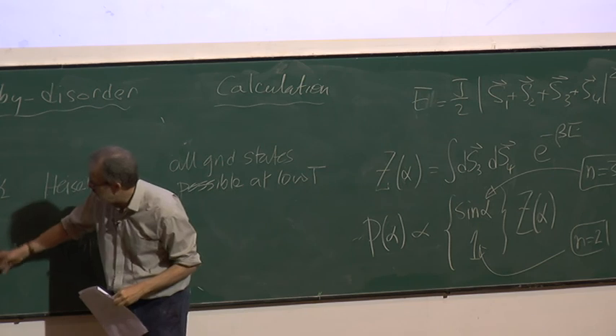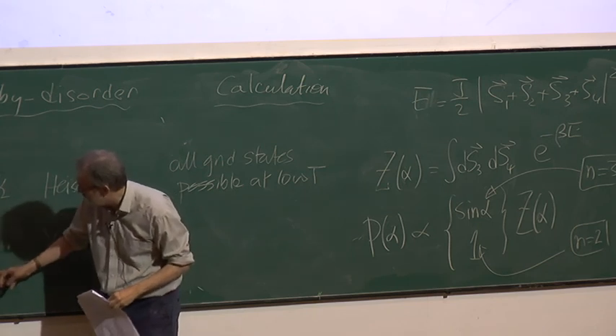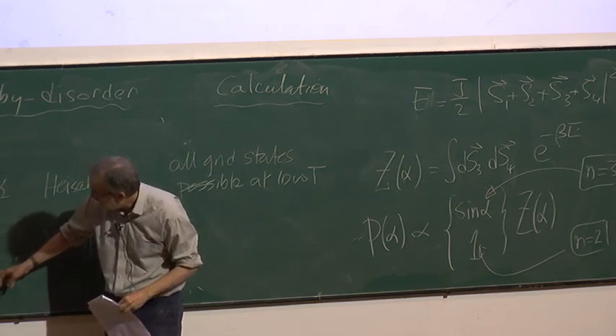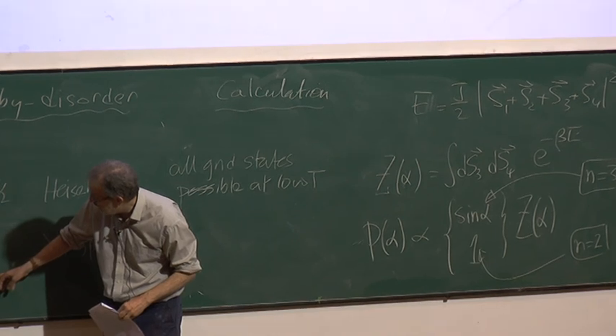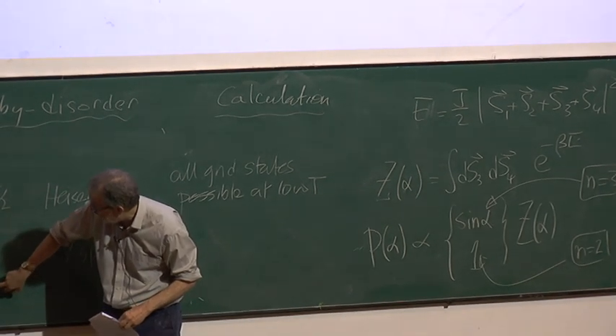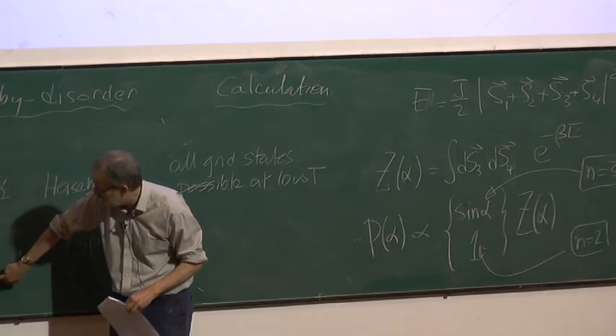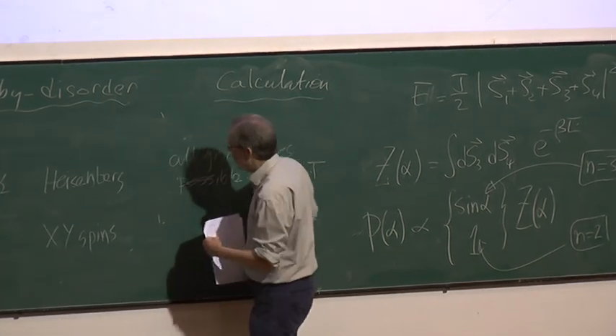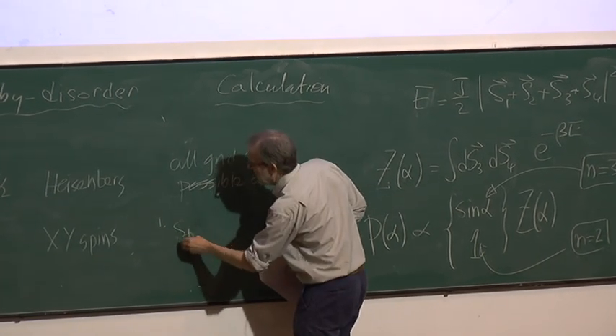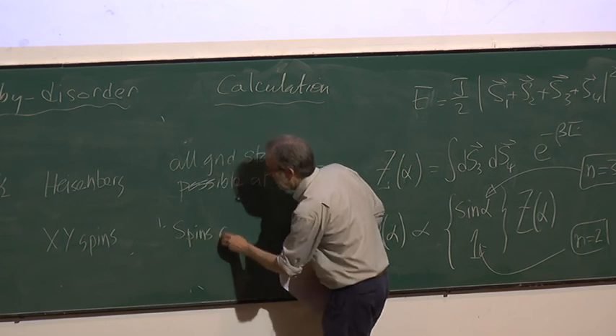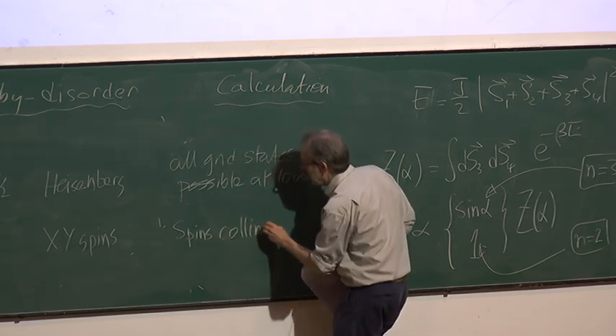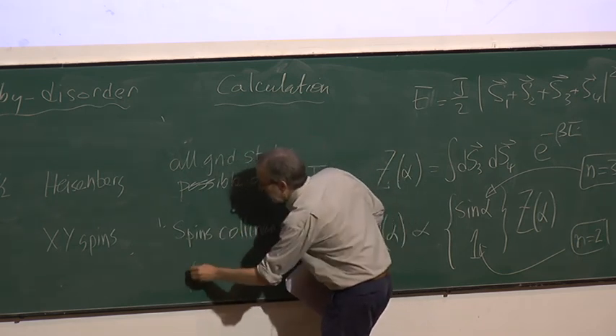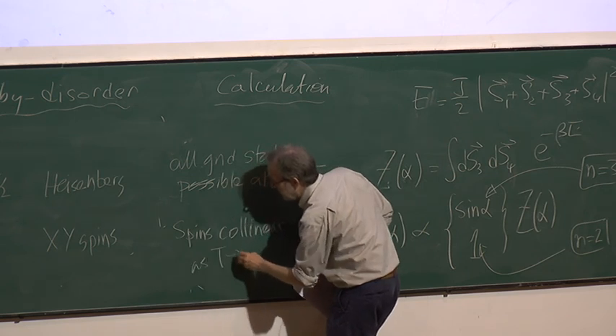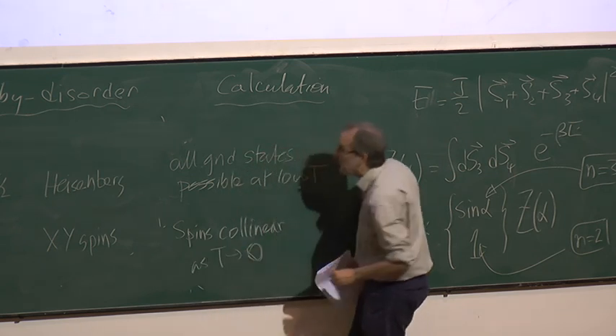Whereas in the case of XY spins, because this has a divergent weight at alpha equals 0 and alpha equals pi, you find that the spins are collinear as temperature goes to 0.